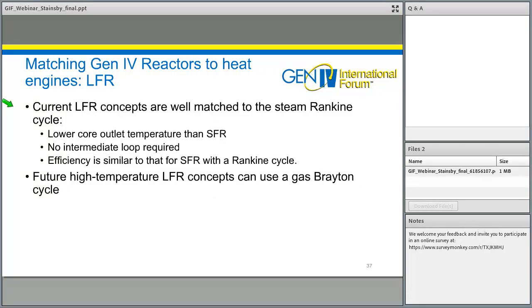the current LFR concepts are well matched to steam Rankine cycles, and currently LFR is limited to quite a low core outlet temperature, probably around 500 degrees C maximum, because of the need to avoid corrosion within the lead coolant. So we get a slightly lower core outlet temperature than SFR, but because there is no violent exothermic reaction between lead and water, they don't actually need the intermediate loop in that system. So we save on some of the temperature drops that you'd normally associate with a liquid metal reactor. So overall, we get an efficiency which is similar to that with a sodium-cooled fast reactor in a Rankine cycle when we're using LFR.